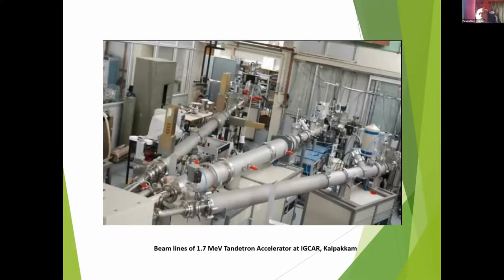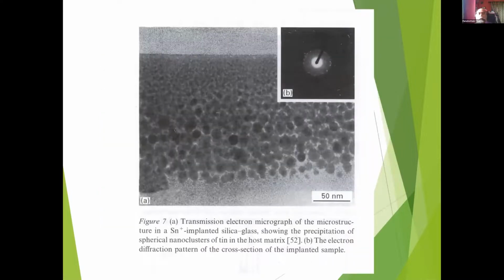Anyway, this is the experimental system. There are many, many beam lines. I have used one single beam line for ion implantation. We are implanting ions at different energies, and we are controlling by ion implantation the distribution of the metal particles in the glasses. These are the metal particles.